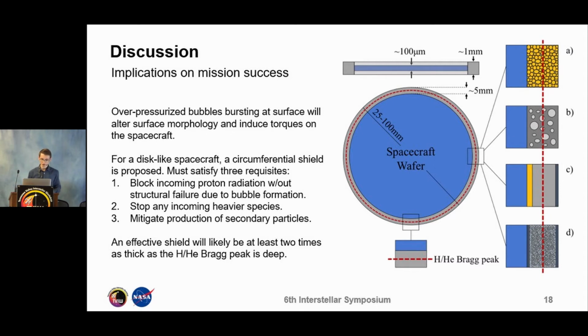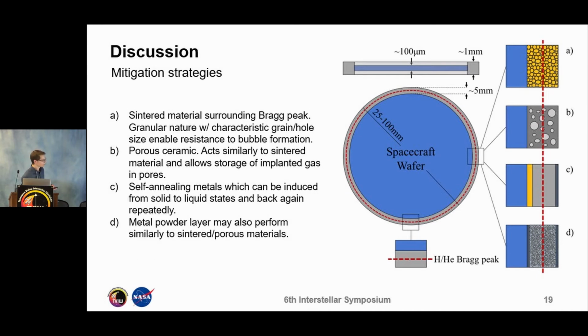Therefore, an effective shield will likely be at least 2 times as thick as the hydrogen and helium Bragg peak is deep, where the Bragg peak is the implantation depth in a given material. If you look at the top right-most version, you have a sintered material. One proposed method is to have a sintered material that surrounds the Bragg peak. The sintered material has a granular nature with a characteristic grain and hole size, which makes it resistant to bubble formation. You can imagine that if a bubble forms within a grain, it will want to burst at the grain boundary rather than migrate to the surface and burst at the surface.